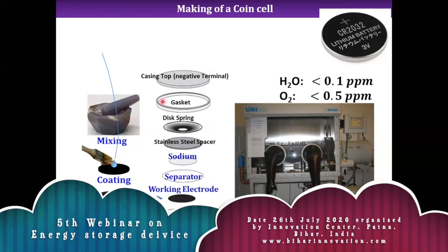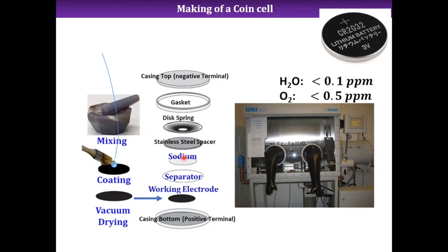And these are the various parts: a gasket to give a tight crimping, conductivity, and a spring, a stainless steel spacer, after that sodium, and then I use a separator, because the separator soaks the electrolyte for a longer time and also gives passage to the ions inside, back and forth. Then I just crimp it, and this cell is prepared. So this is how I make a coin cell.